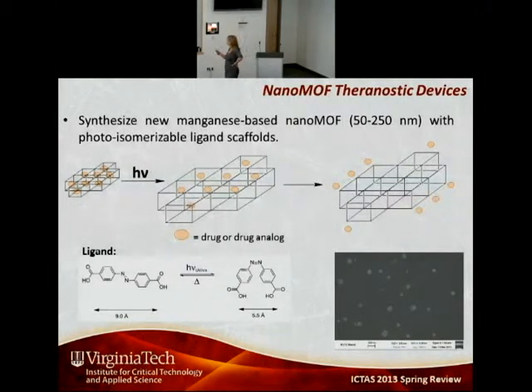Currently, because we are ideally interested in using this as an imaging agent as well, on the metal side we incorporate the manganese ion, and as a linker, different variations of this isomerizable ligand. You can see that the ligands are capped with carboxylic acid moieties, which then coordinate to the metal centers. And these are the SEM images of some of the nanoparticles that we made.